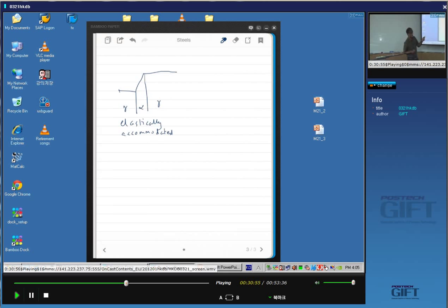But this is quite a large deformation. If we are at a high temperature where the austenite is mechanically weak, then it will tend to relax by plastic deformation. So instead, you get a shape deformation which is nice and clean where the plate is, but then you get a rough relaxation. And here we have the plate of alpha, gamma, and gamma. And this is plasticity.